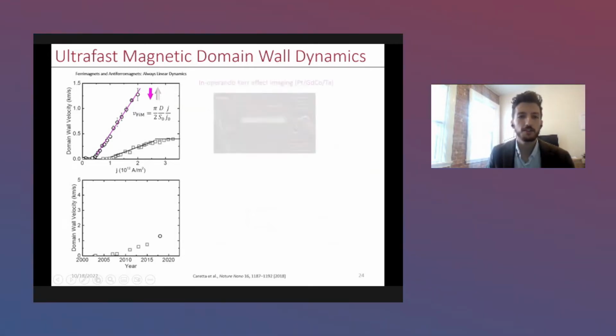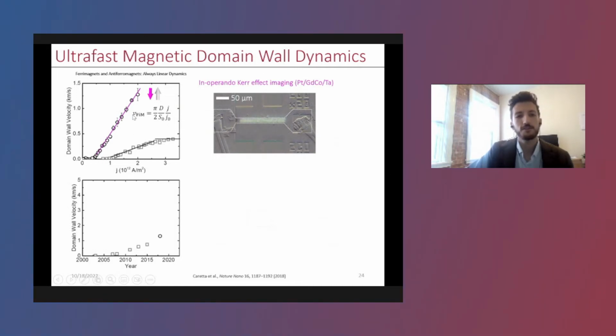Not only that, we've actually even reduced the critical current densities required for motion and even increased the mobility of the domain walls, with the slope of this curve. And this is really enabled by in situ measurements, operando Kerr effect measurements, as seen on the right.